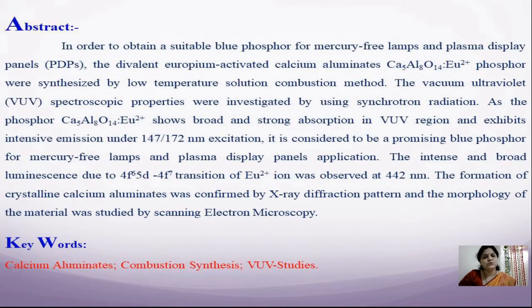Abstract: in order to obtain a suitable blue phosphor for mercury-free lamps and plasma display panels, the divalent europium activated calcium aluminate Ca5Al8O14:Eu2+ phosphors were synthesized by low temperature combustion method. The vacuum ultraviolet spectroscopic properties were investigated by using synchrotron radiation. As the phosphor Ca5Al8O14:Eu2+ shows broad and strong absorption in the VUV region and exhibits intensive emission under 147 and 172 nanometer excitation, it is considered to be a promising blue phosphor for mercury-free lamps and plasma display panels application.